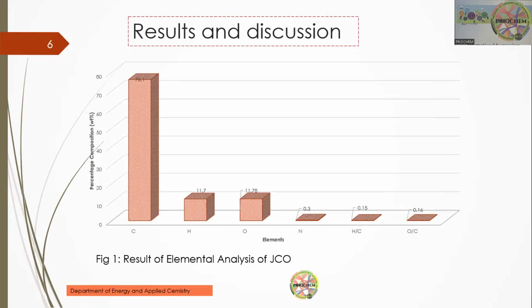We find out the carbon is around 76%, with hydrogen and oxygen nearly the same, then the nitrogen at 0.3%. Our concern here is the oxygen to carbon ratio. We expect at the end to reduce this oxygen to carbon ratio after the deoxygenation.